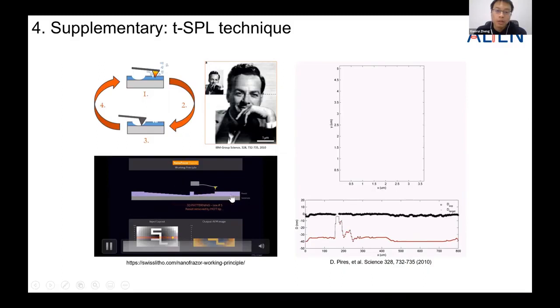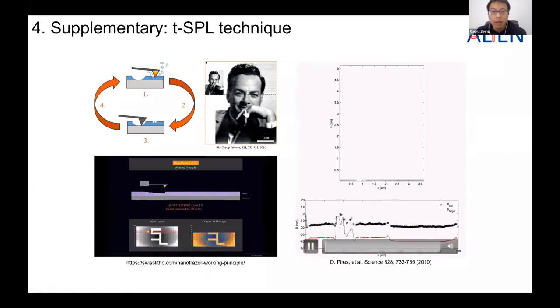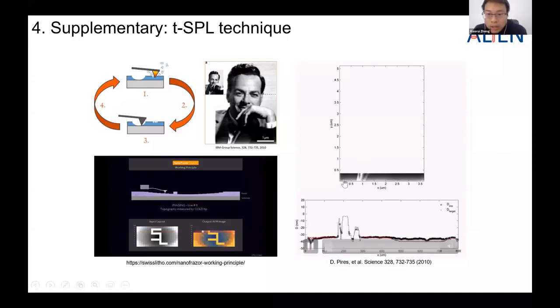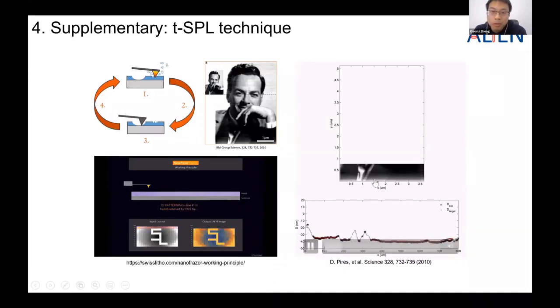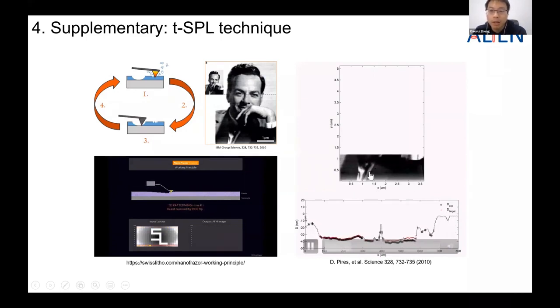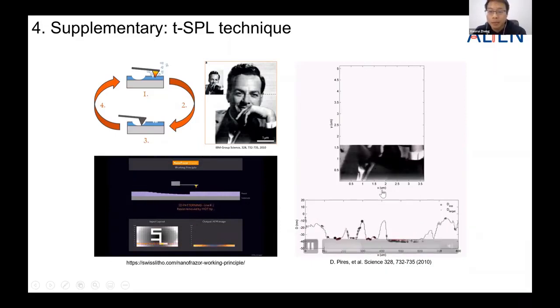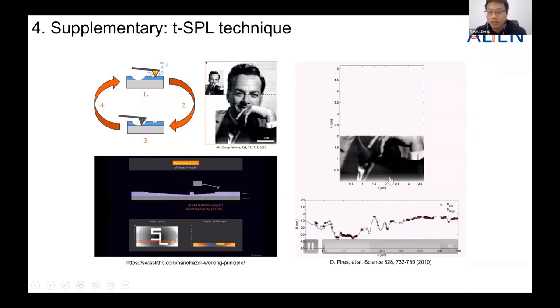By comparing the structures, we could introduce computer assisted programming parameter optimization in order to achieve the best closed loop lithography. And this is an example by comparing. As you can see, in the first few lines, the fabricated structure has a difference compared to the design. But after a few pixels, you would have self adjustment of the parameters, and then we get a perfect image compared to the design. Why is this important? Because in certain applications, this 3D patterning is very critical.